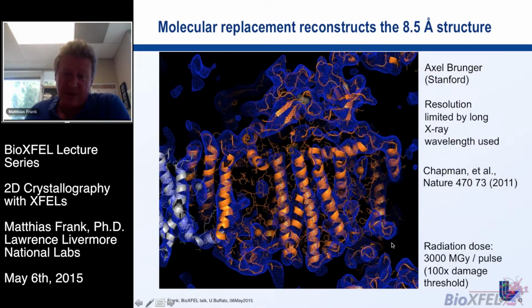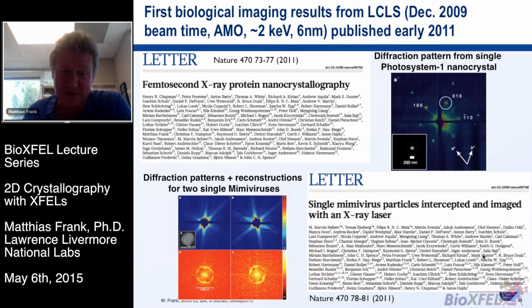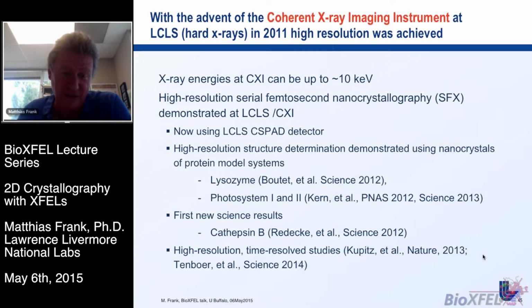They also calculated what the radiation dose was that these proteins were exposed to. It was about 3,000 megagray, which is 100 times above the damage threshold that usually limits measurements at synchrotrons. Of course, when you have larger crystals at synchrotrons, you can always move to a fresh spot in your crystal and get around the radiation damage to some extent that way. So these were the 2 papers I mentioned, on protein nanocrystallography and on the imaging of single mimiviruses.